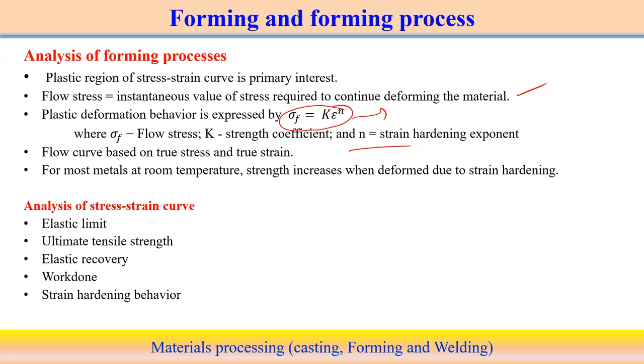The flow curve is based on the true stress-strain diagram, which is more important in the plastic deformation zone. Most metals at room temperature show increasing strength when deformed due to strain hardening. Plastic deformation starts at the yield point, and if you gradually deform the material beyond it, the strength level increments. Taking the logarithm of sigma_f = k * epsilon^n gives: ln(sigma) = ln(k) + n*ln(epsilon). Plotting ln(stress) vs ln(strain) gives a linear relationship where the slope n indicates the strain hardening coefficient.